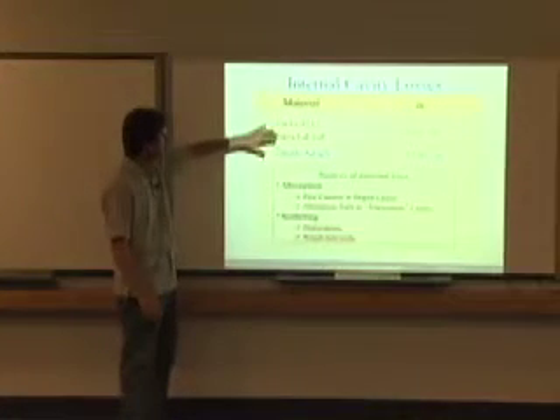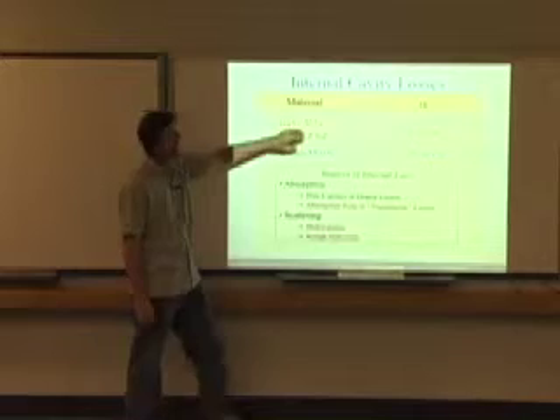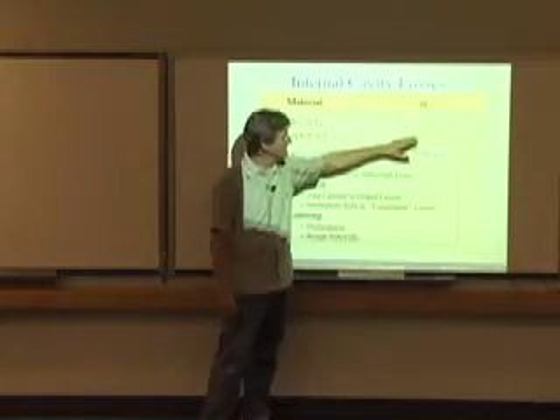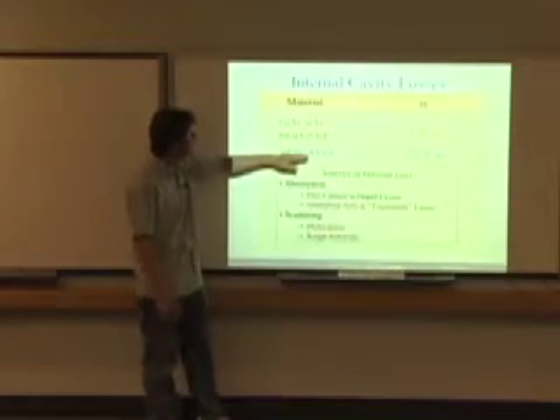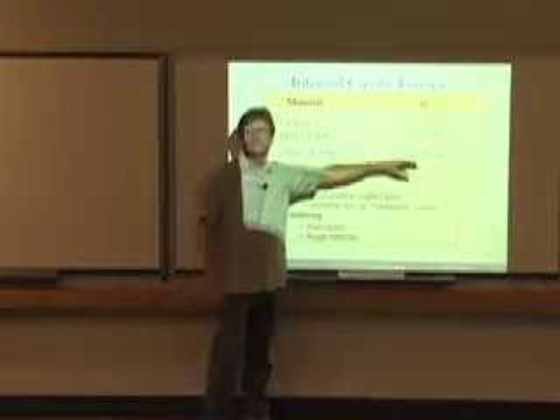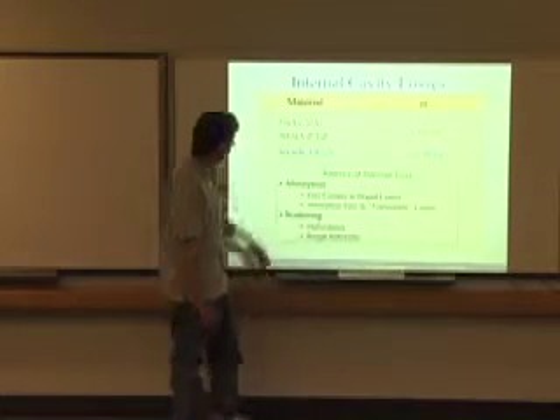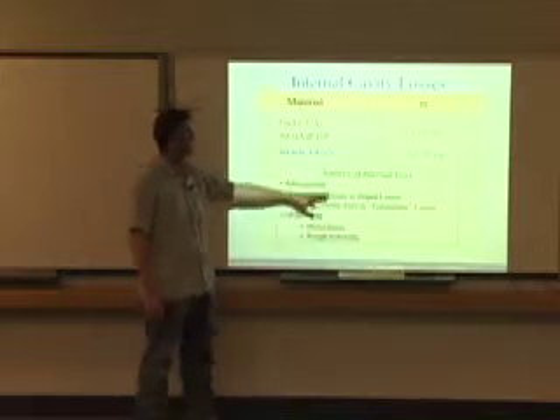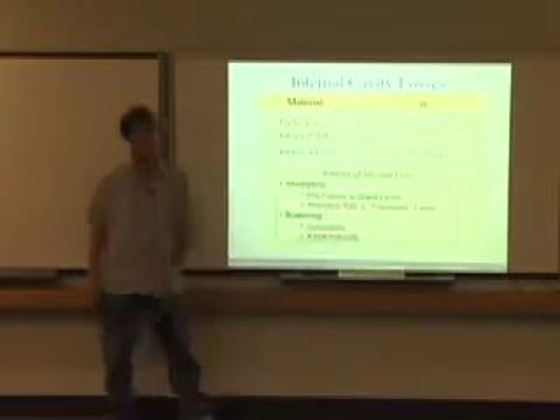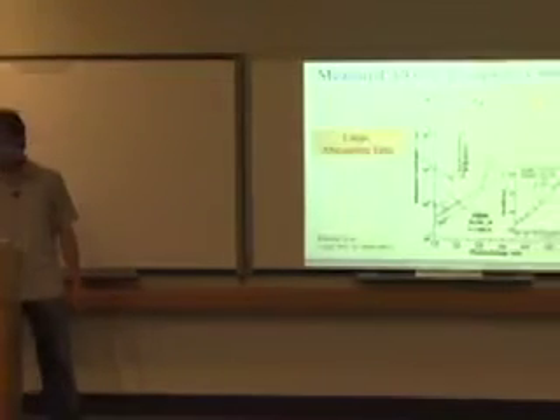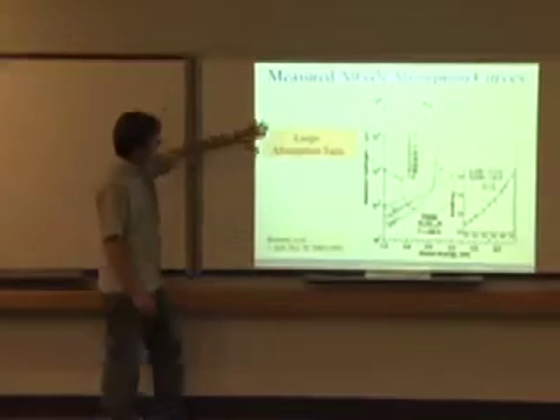If you look at gallium nitride, if you look at AlGaAs, your internal losses are generally in the range of 3 to 10 inverse centimeters. At the time, the InGaN, AlGaN structures were in the 35 to 50 inverse centimeters loss range. And it wasn't just free carriers in the doped layers, but it was also absorption tails that were occurring in the transparent layers. And this is an example of one person's.